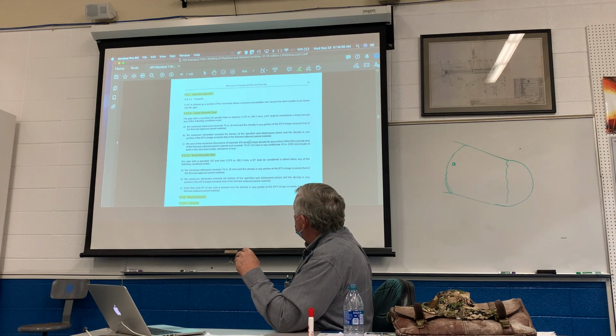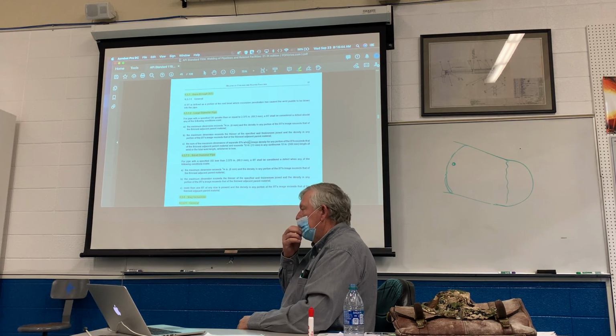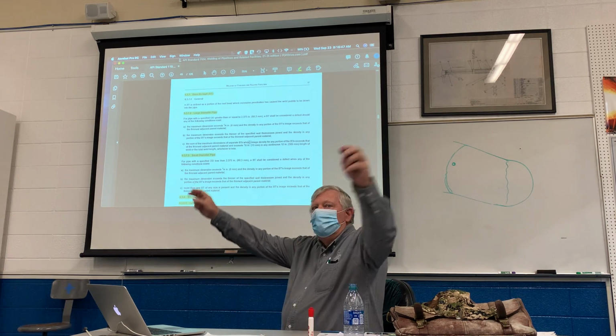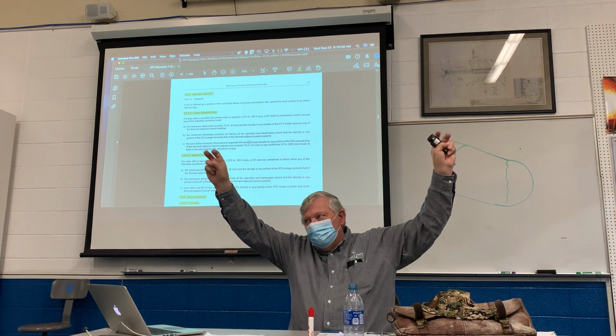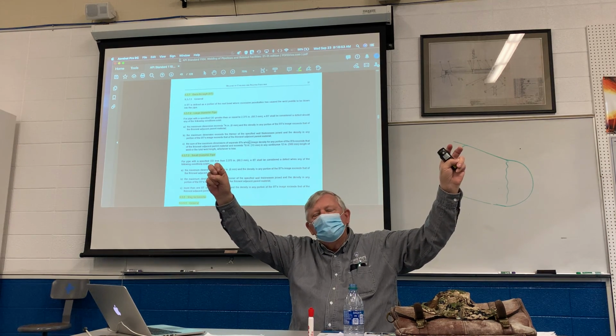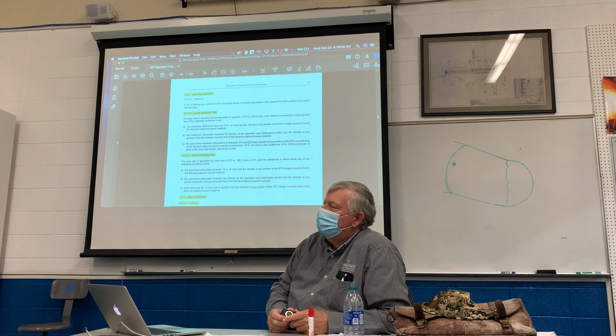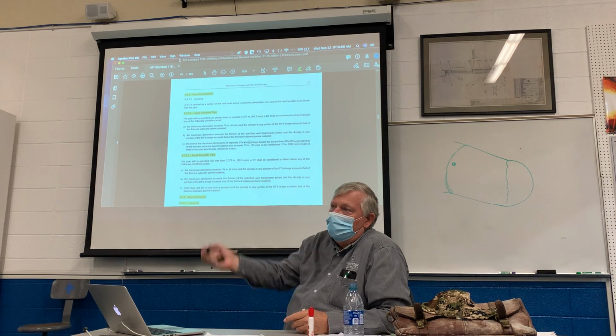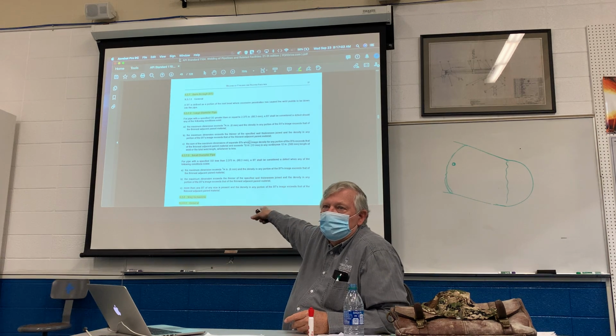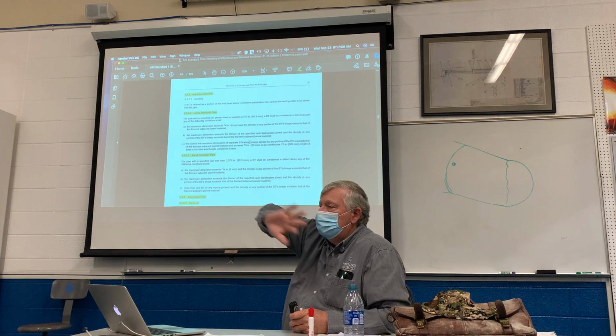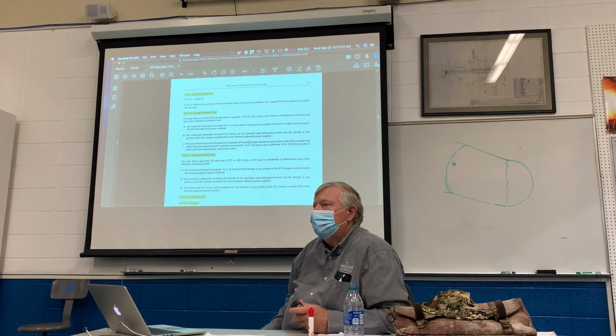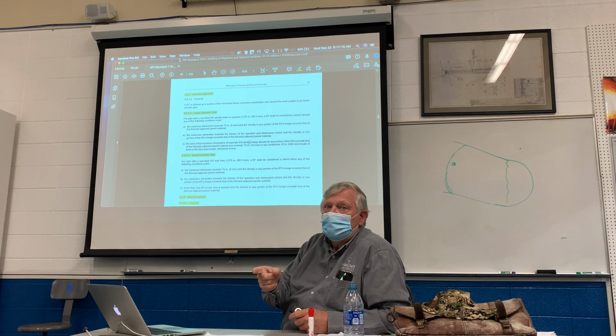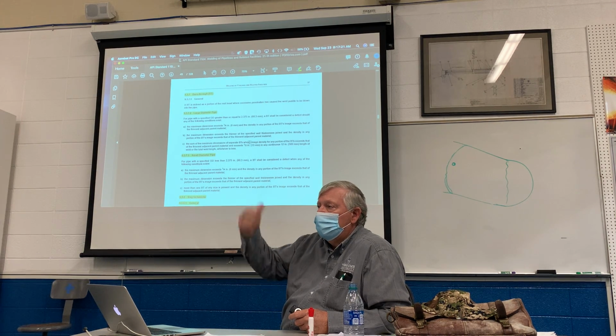And then the sum of the maximum dimensions of separate BTs, and this is what you see more than anything. Because you get these guys that run all over the country, and they're hot pass hands. That's what they call themselves. I'm a hot passer. They're famous for really welding the hot second pass, but they produce burn throughs all over. I've had to shut several of them down and tell them, you're going to have to change this completely. This is totally out of spec. Yeah, but this is the way I run it. Yeah, I can't do it because I'm done seeing burn throughs on this work. So you get that under control. You do one more burn through and you're gone.